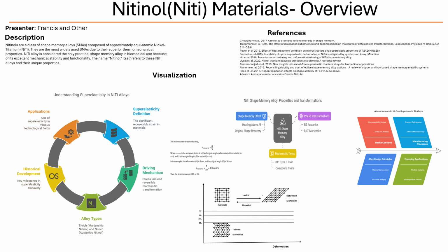Another important factor, especially for bone implants, is how well these materials can dampen vibrations. The closer the damping characteristics of the implant are to those of the surrounding bone, the better the implant will integrate with the bone. And some studies have even shown that superelastic NiTi can actually promote bone growth better than those conventional titanium alloys that don't have that superelasticity. This might be because it's better at distributing those mechanical stresses. So the hunt for that perfect nickel-free superelastic alloy, it's a really exciting area of research.